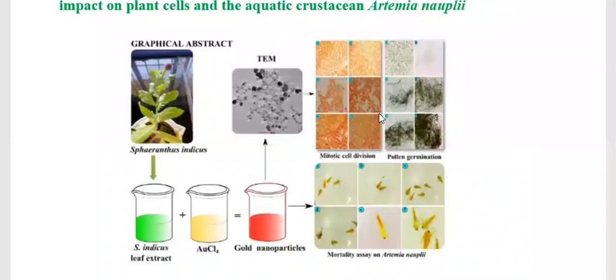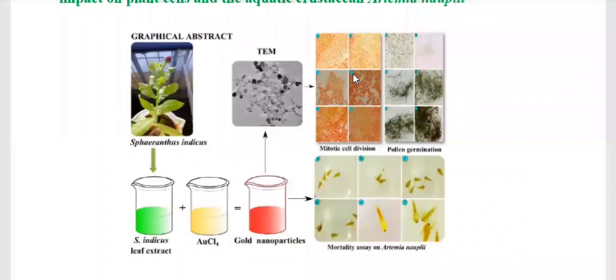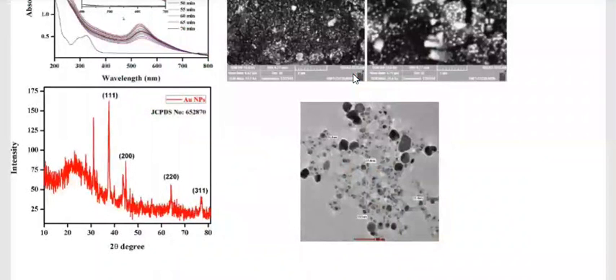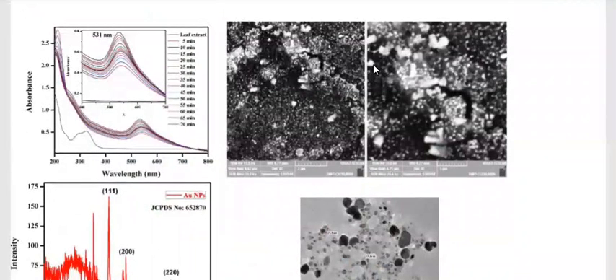It shows leaf extract, generally known as Sphaeranthus indicus, 10 gram of this one. The UV analysis shows 531 nanometers and the same analysis shows spherical morphology. The XRD shows a highly crystalline nature. TEM also shows the spherical morphology.